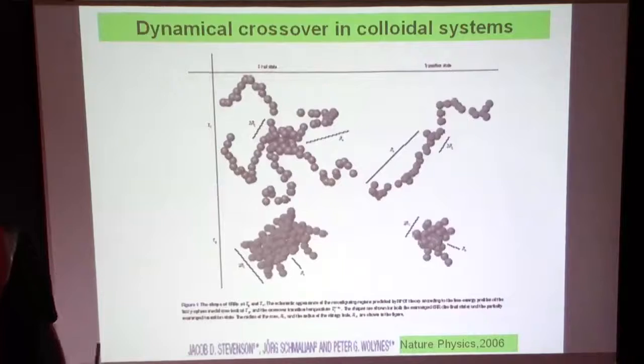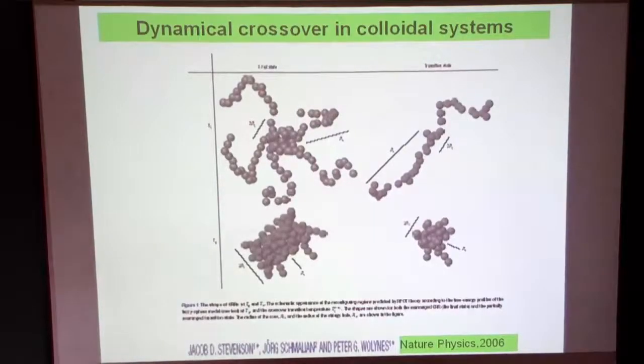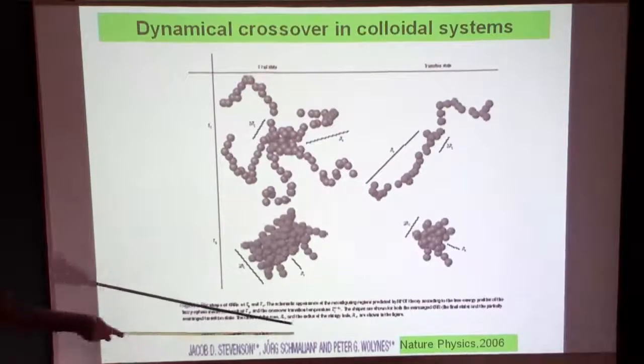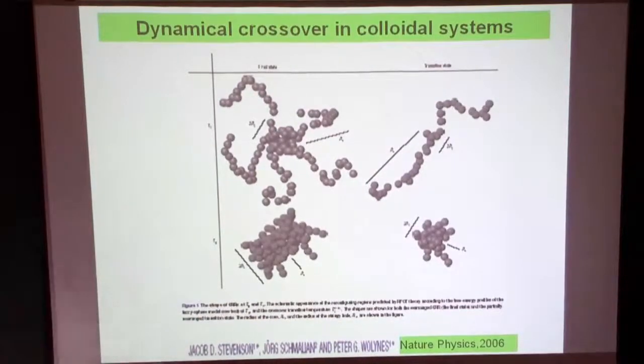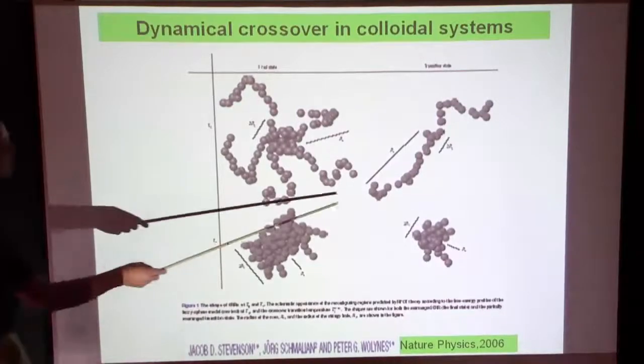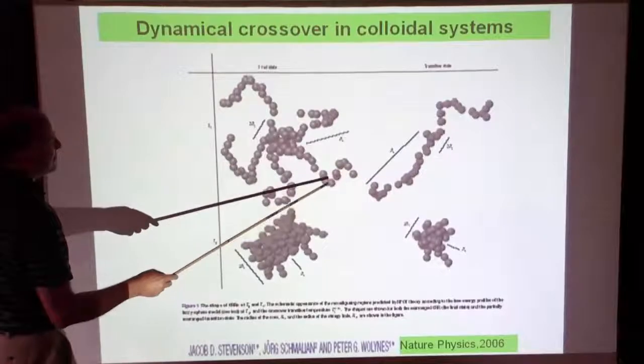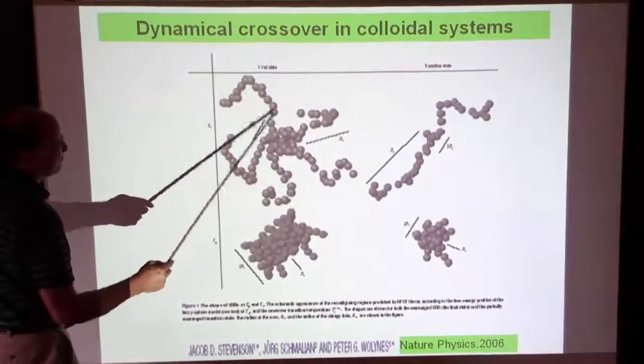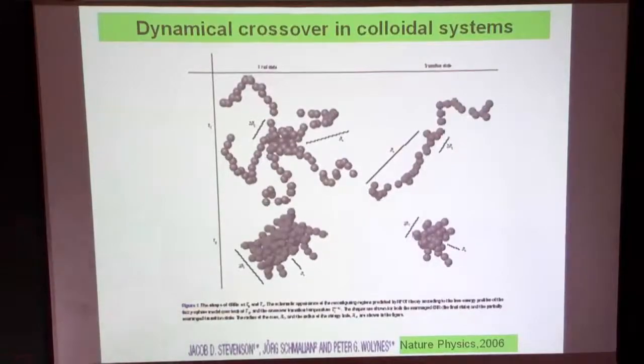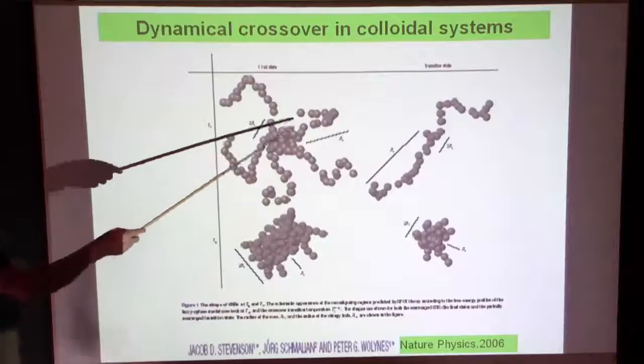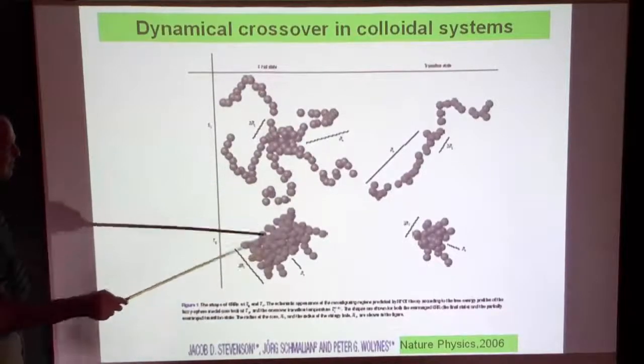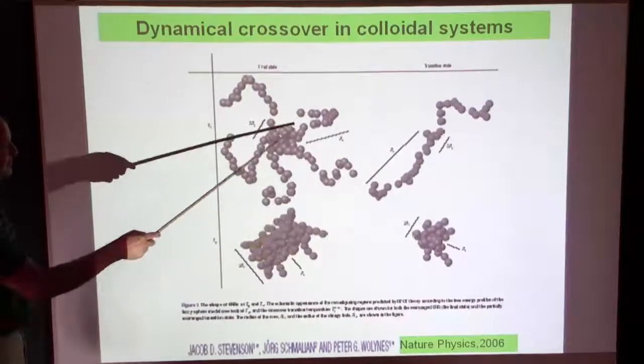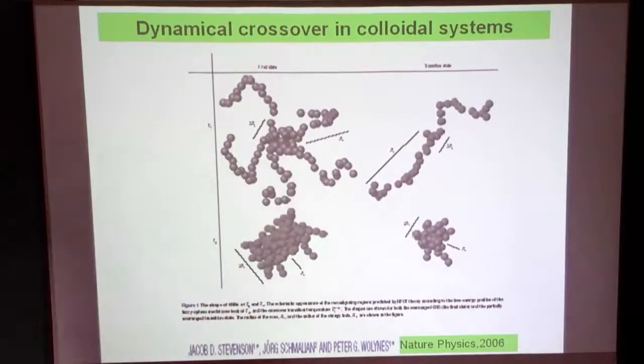Okay, since we had so much discussion about the colloidal system, I put some slides in from previous work from Peter Wolynes's group here in 2006. They found in colloidal systems some kind of string-like structure and this kind of octopus, whatever it is, which they also call a transformation. And what they also showed is that if you increase the rate of shearing, and also in our case the temperature later on, these objects get smaller and smaller. And at the very end, they all have to be ballistic. At the very end, this liquid becomes a gas, ballistic, so they have the single atom at the end.